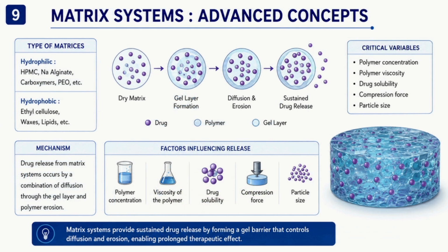Matrix systems, advanced concepts. Matrix systems are particularly important because they are widely applicable to oral controlled release dosage forms. Hydrophilic polymers such as HPMC can form a gel layer when exposed to aqueous media. The sequence is water penetration, polymer hydration, gel formation, drug dissolution, and erosion. Initially the water penetrates through the outer region, and the polymer hydrates and forms a viscous gel, and the gel creates a diffusion barrier. As time progresses, the gel layer becomes thicker and the drug diffuses through this hydrated polymer. Eventually, polymer erosion may contribute to release.